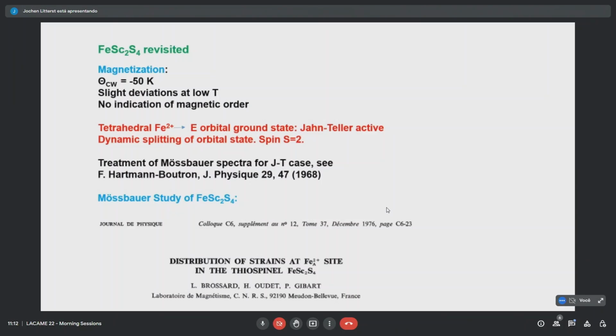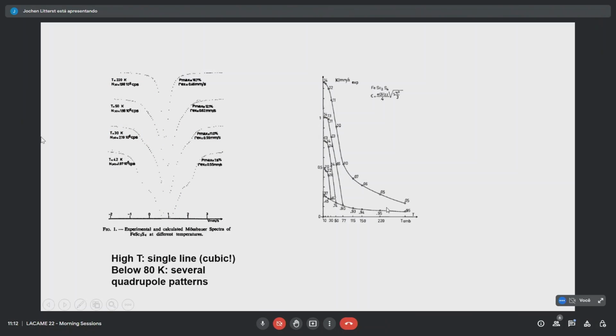Now, back to iron scandium sulfide. What did he see? Sorry, the spectra on the left are very bad to see, but I checked once against the original, and it's not much better. You see, at high temperature, you think that it's non-magnetic. And if you go lower, it's broadening. Below 80 Kelvin, Brossard's interpretation was that this is the development of several quadrupole interactions due to local disorder, due to local distortions, which come along because of this peculiar orbital state.